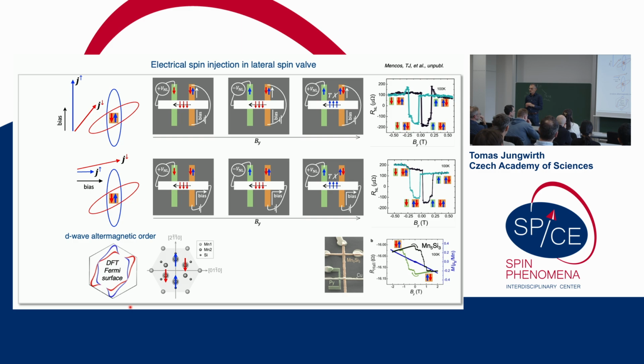So that does not contribute. So we may have more of these variants in the sample because we don't have good control, but we know that the net effect would be a net spin polarization. Yeah, so it would be different domains. But at some lower temperature, you would expect that the entropy that these two non-ordered spins have should lead to another ordering.